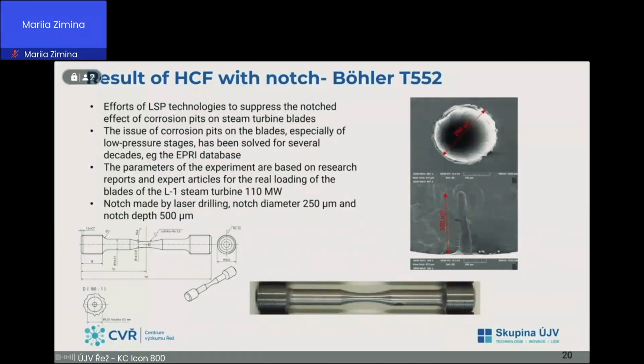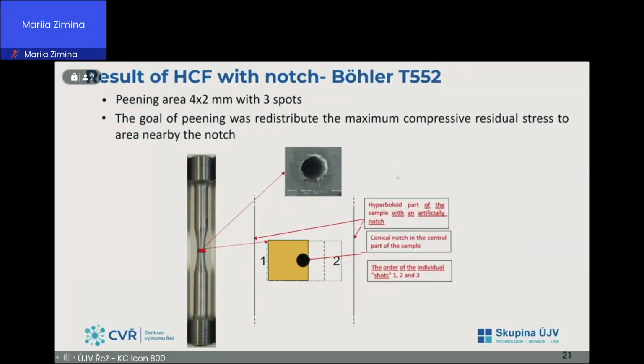The artificial notch was made by laser drilling. The diameter of the notch was 250 microns and the depth was 500 microns. And there is a specimen. We used a peening strategy. We used only three shots, as you can see in the animation. And the peening area was 4 × 2 millimeters with 3 spots. The goal of peening was redistribution of maximum compressive residual stress to nearby the notch, because we know how the crack initiates and how it propagates.